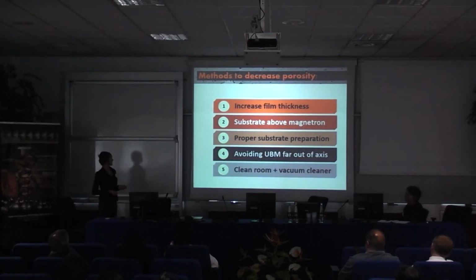And of course, for whatever process, you can try to decrease porosity by increasing film thickness, placing substrate above magnetron if it's possible, and proper substrate preparation means cleaning, etching, etc. Avoiding, in a case of unbalanced magnetron, a position far out from axis, if it's possible, and use of clean room and vacuum cleaner to remove all metallic particles from the chamber.